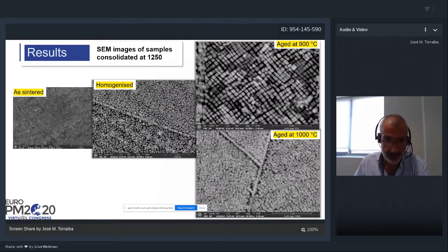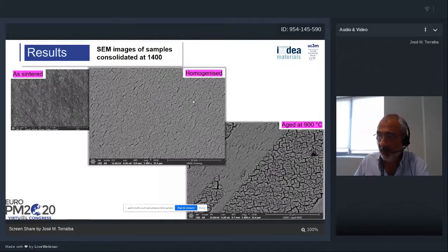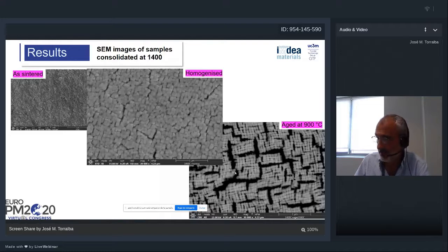detailed study. And also for the higher temperature, we have a very well developed structure with the gamma prime cuboid precipitates in the gamma matrix. At higher magnification, we see some clusters of gamma prime with some bigger channels of the gamma phase that maybe will affect the behavior at high temperature.